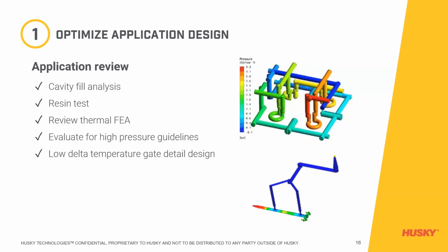Evaluate the need for a resin test. This is something we typically do at Husky, especially if it's a new version or a new bioresin that we haven't encountered before. We will request some resin into one of our labs and we'll do a resin test. This is usually recommended for resins with limited performance data or for particularly challenging applications. Evaluate the bioresins for any guidelines on maximum pressure. Review the low delta temperature between the tip and the gate, which could cause leakage issues, something we need to pay attention to.